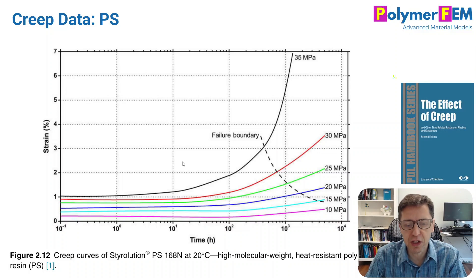From these results, I can extract the failure time corresponding to each stress level and plot them. The result, shown directly from MCalibration, is the creep rupture stress as a function of logarithmic time. With the TNV model from the PolyUMod library, I get the same type of response seen experimentally — almost a straight line — allowing prediction of creep rupture across a wide range of stress levels.